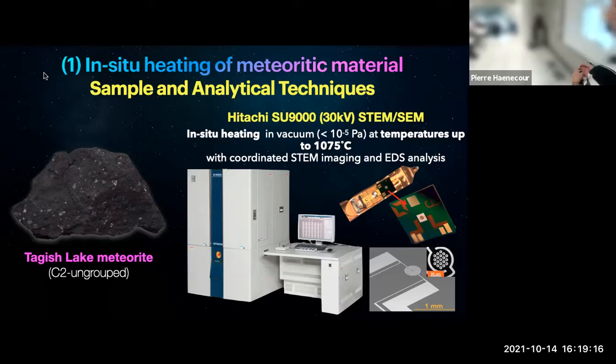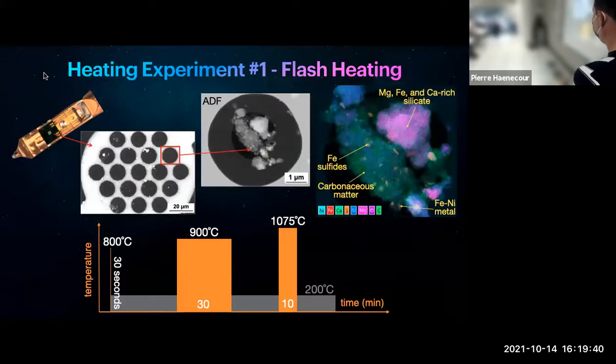they were slowly heated. The way we did it is in vacuum, in the SEM itself, at temperatures from room temperature up to just over 1,000 degrees. You can do it in any step you want, and you can heat the sample for several hours. So we did different types of heating regimes. You can see here, the first one was a flash heating. We flash heated the sample to 800 degrees in less than 30 seconds, then put it back to room temperature and did some imaging. We did the imaging at 200 degrees.